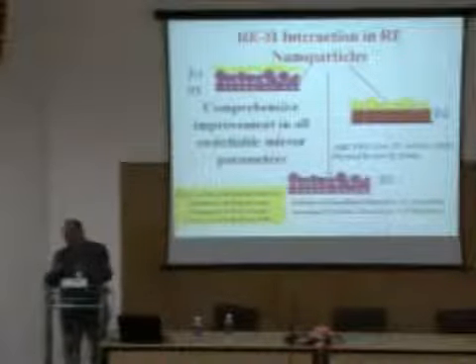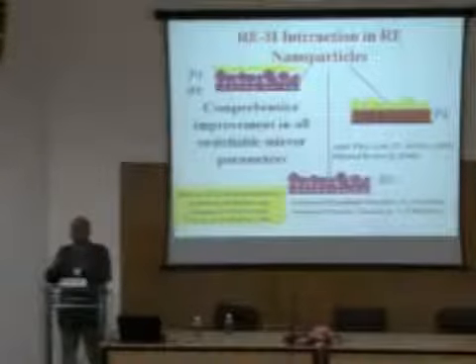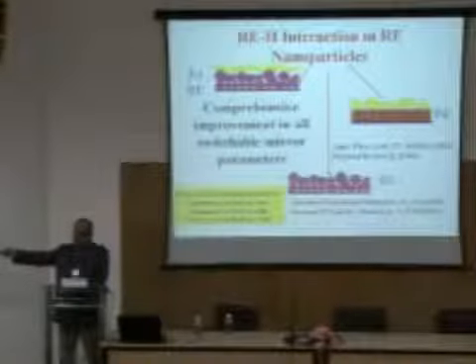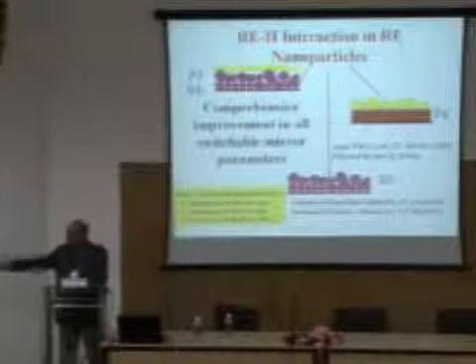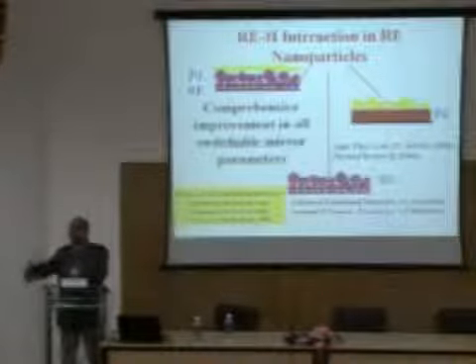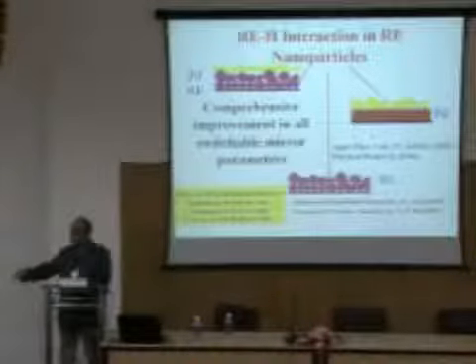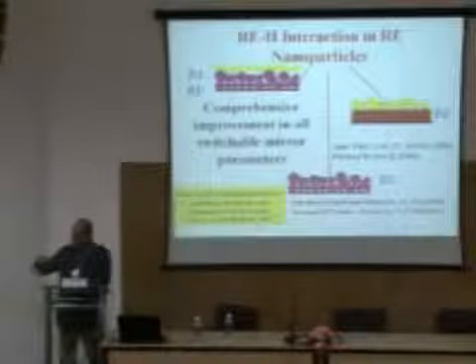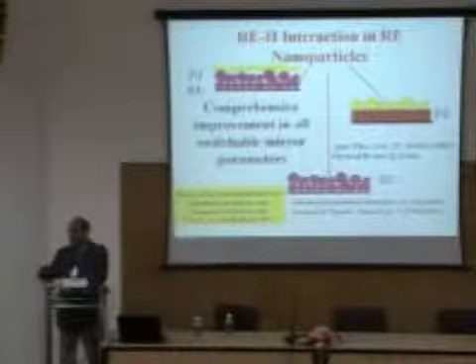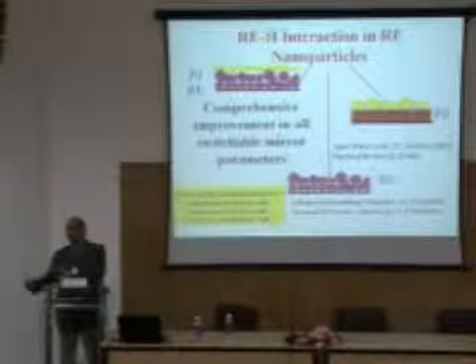The second system which we tried to investigate, as I already mentioned, is that rare earth materials are highly susceptible to oxidation. If a thin film reacts with oxygen very quickly, nanoparticles will react even faster. Just like we expect nanoparticles to react faster with hydrogen, we should also expect nanoparticles to react more with oxygen. So we were very much concerned about the stability of rare earth nanoparticles in oxygen. So we wanted to investigate what happens when you go from thin films to nanoparticles. Let's expose these particles to oxygen.